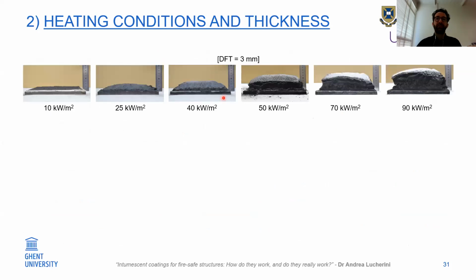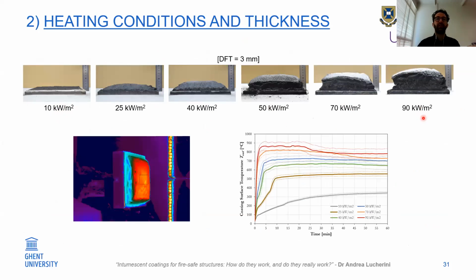So these are, for example, some chars that I obtained at the end of my experiments, completely different chars with completely different swelling. Of course, not much swelling for the case of 10 kilowatt per square meter and a very thick porous char in the case of 90 kilowatt. In terms of surface temperatures, you can see that the intumescent coating behaved as an insulation material, as a thermally thick material, where, depending on the incident heat flux, the intumescent coating goes into a sort of steady state condition on the surface, so a sort of constant temperature at the surface based on the applied incident heat flux.